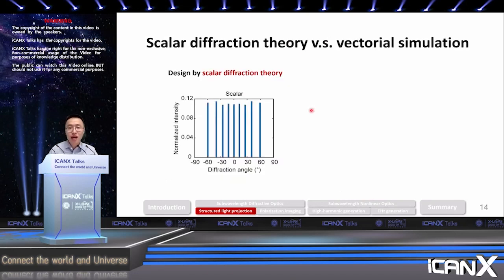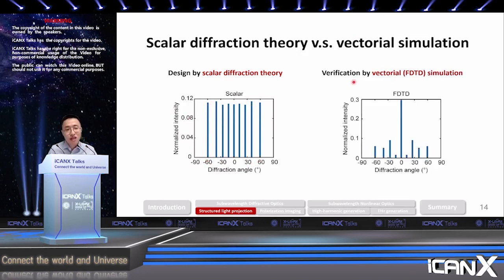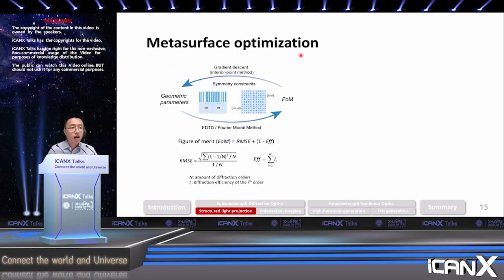To prove that, we first designed our metasurface simply by scalar diffraction theory, and we found that we can get a very nice and uniform diffraction intensity all the way from minus 60 to plus 60 degrees throughout all these 9 orders. But later we tried to verify this result by vectorial finite-difference time-domain simulation, and you'll find the result becomes completely different from what we predicted from scalar diffraction theory. With that, we think we need to find a different method for the metasurface optimization.